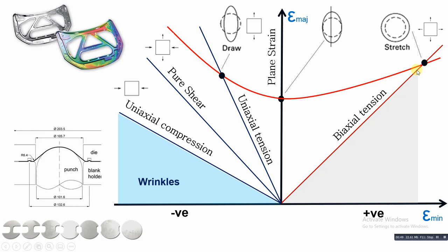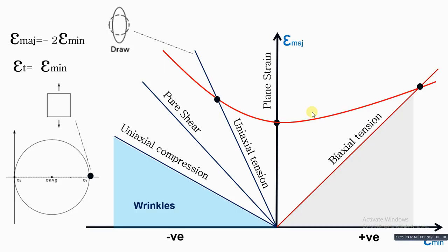So the forming limit curve here is the failure criterion we were looking at all the time. And as a margin of safety, we should make an offset of about 10% of the values of the forming limit curve. So we need to make an offset here, and we need to draw another curve here below. We will not call it the forming limit curve. We will call it the safety or the safe margin curve, to guarantee that any element must be far from the necking region. Okay, let's recap all we discussed in the forming limit diagram.